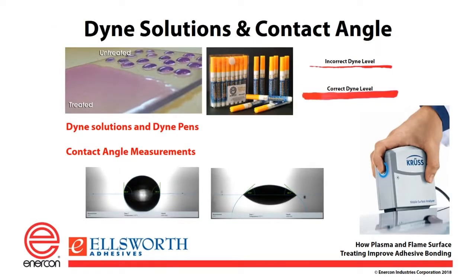Here's some pictures of those methods we were talking about. On the top, you can see the Dyne pens, and then on the right there, you see Dyne ink, used either with a pen or with the ink. And what you do is you run a line across the surface, and if it starts to bead up, like it does here in the incorrect Dyne level, so let's say you're using 50 Dyne in this example. Well, at 50 Dyne going across there, that would be a fail. So that means that your Dyne is actually lower than that.